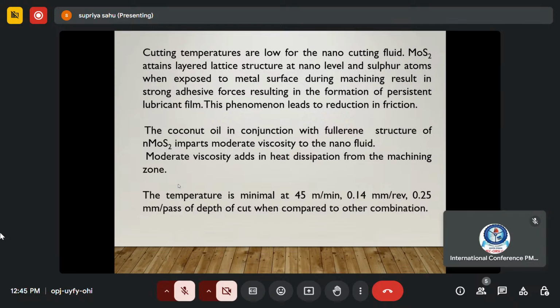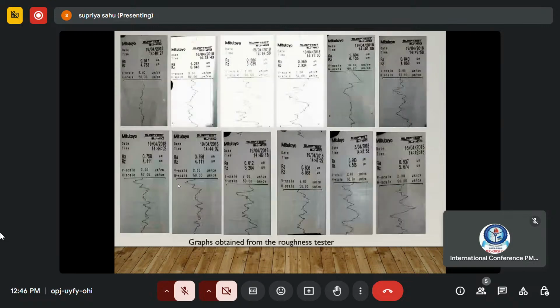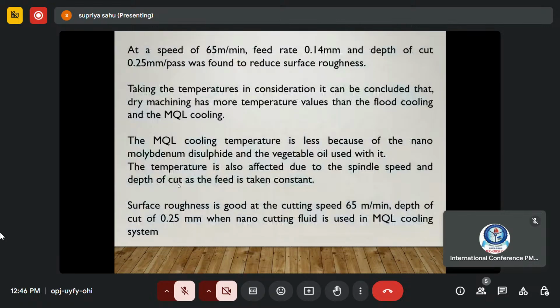The coconut oil, in conjunction with the fullerene structure of the nano MoS2, imparts moderate viscosity to the nanofluid. The moderate viscosity aids in heat dissipation from the machining zone. So here the temperature is minimal for the speed of 45 meters per minute, feed 0.14 mm per revolution, and depth of cut 0.25 mm per pass when compared to the other combinations. So these are the graphs obtained from the surface roughness tester. At the speed of 65 meters per minute, feed of 0.14 mm and depth of cut 0.25 mm per pass, it is found to reduce the surface roughness.